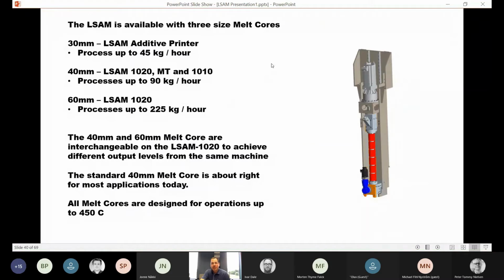The LSAM is available with three size melt cores. The smaller LSAM additive printer, like I mentioned before, comes with a 30 millimeter melt core. It has the ability to process up to 45 kilograms of material per hour. The 40 millimeter melt core is our standard melt core, and that's just about right for most applications today. That comes standard on all our other equipment, including the LSAM 1020, the MT, and the 1010. This processes up to around 90 kilograms of material per hour.